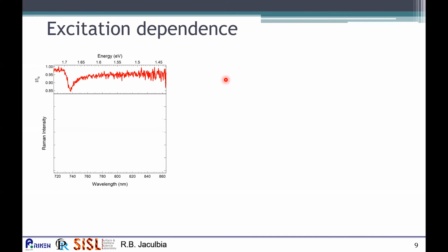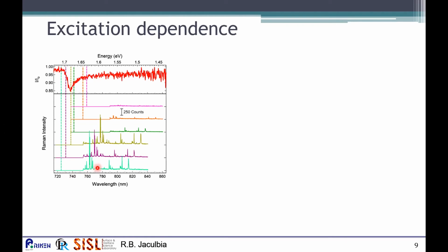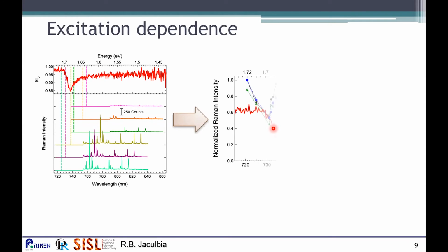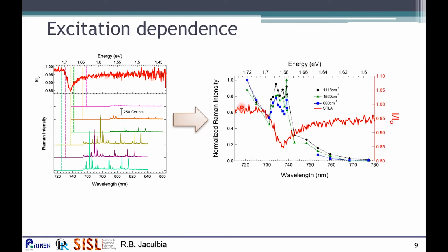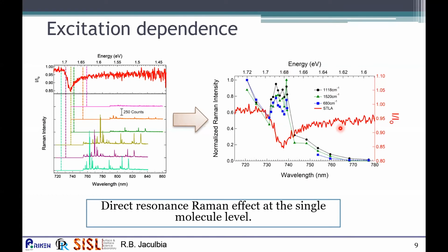So now that we know the absorption of the molecule, we tried to vary the excitation wavelength of our laser in order to observe the resonance Raman effect. What we did is we changed the wavelength of the excitation laser in this wavelength range, and we observed the individual Raman signals. And when we plot the vibrational peaks, we can observe such a plot. Here we can see that the absorption results nicely match the Raman signals of selected peaks. In fact, all the peaks follow the same trend. This is a clear evidence of direct resonance Raman effect at the single molecule level, which has not yet been shown previously.